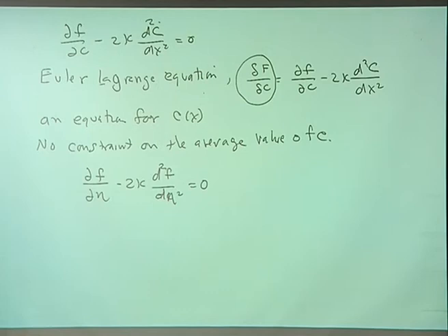Okay, and you could do that with an order parameter, but for composition you have the problem that, wait a minute, I have two phases. I can't make the composition uniform every place because I have a conservation. What that means is that when we derived this equation in terms of composition, we left out a constraint, and that constraint is one on the average composition. So this is perfectly okay for an order-disorder transformation.